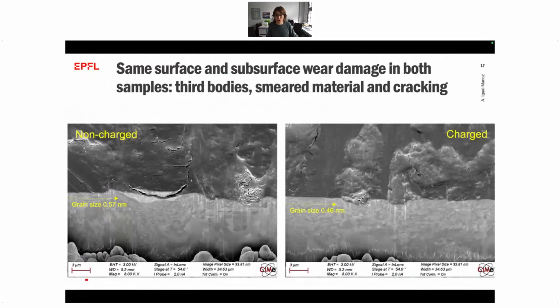And if we do again the cross section, this is the sliding direction. Here also at the subsurface level, we see more or less the same features. We see this third body. We see this smear material. We see cracks, subsurface cracks, surface cracks. So basically, we see more or less the same effect, same grain sizes.